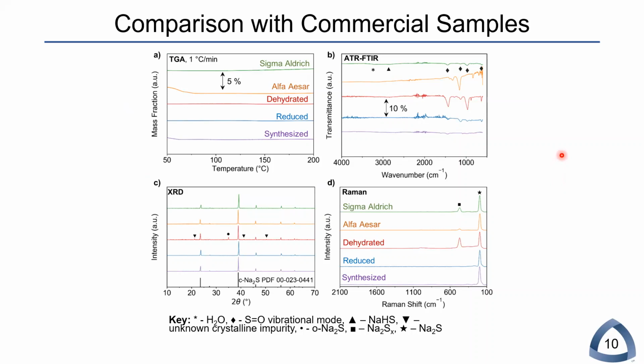So to put everything together, we compared the hydrogen reduced and the synthesized materials to 2 commercial samples from either Alfa Aesar or Sigma Aldrich, using a complementary suite of characterization techniques including TGA, FTIR, XRD, and Raman. And we found that FTIR and Raman were the key characterization techniques since they can easily detect the presence of oxysulfur and sodium polysulfide species respectively. And we found that the reduced and synthesized materials were at least comparable to, if not superior to, both the commercial samples in all characterization techniques that were used.